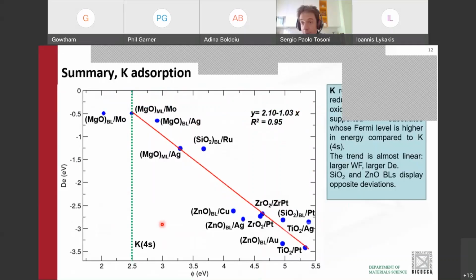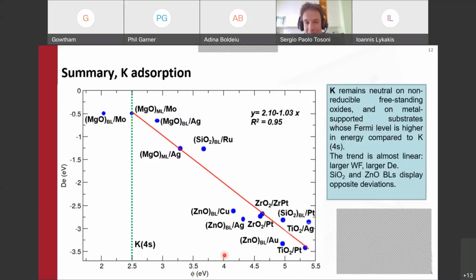Let me try to summarize. In this plot, I'm reporting the adsorption energy of potassium on all the substrates that I have mentioned and described up to now, as a function of the work function of the substrate. And this green dashed line is the energy of the 4s orbital of potassium.